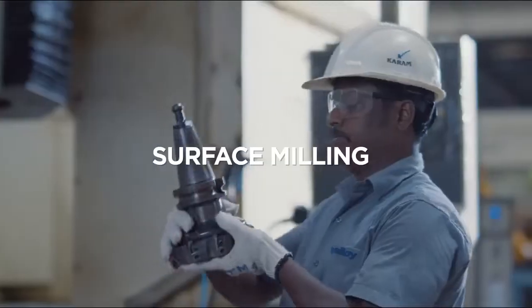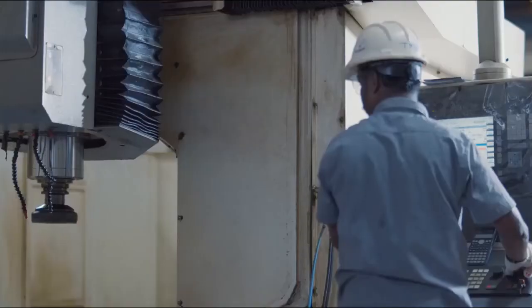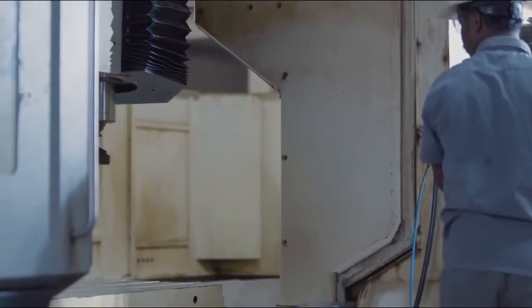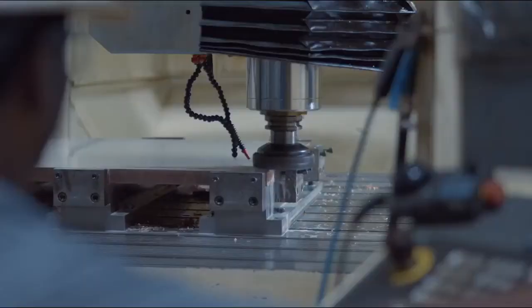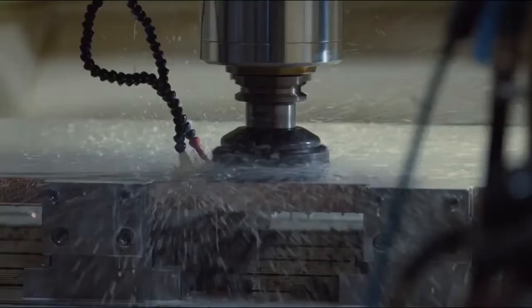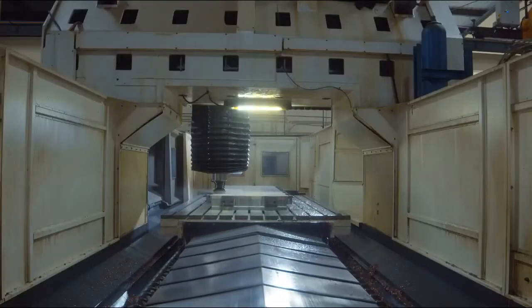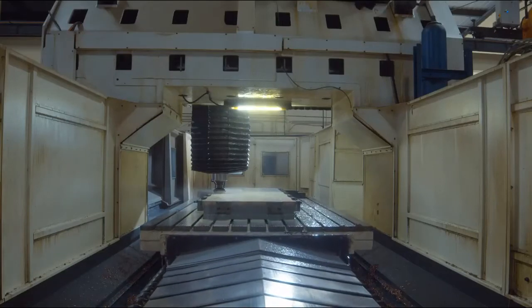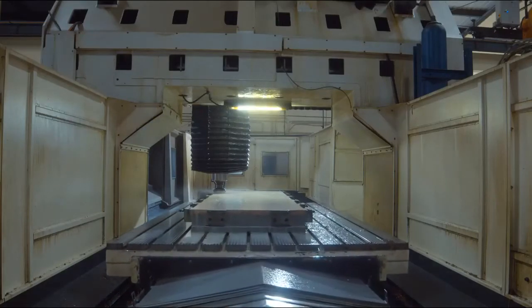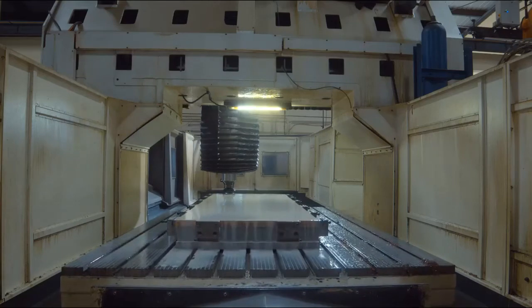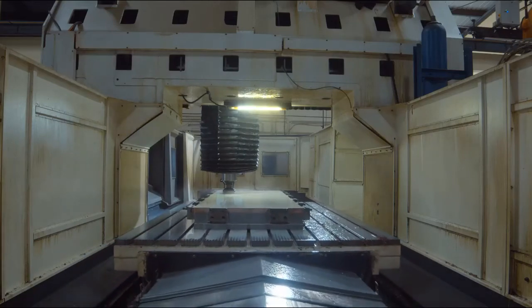After heat treatment, surface milling is done in one of our many vertical machining centers. We can machine and remove hard metal quite easily at high speeds. We can handle a size of 2200 millimeters width, 3200 millimeters length, and a height of 800 millimeters.